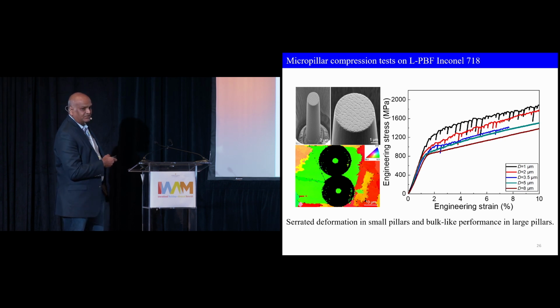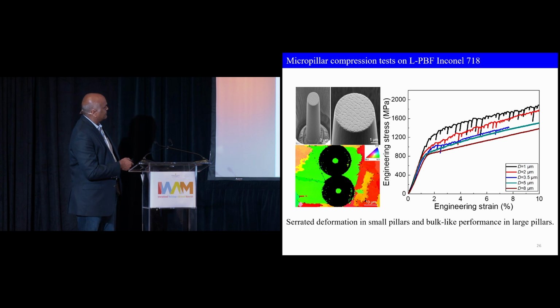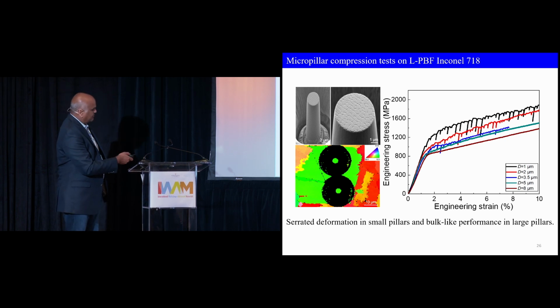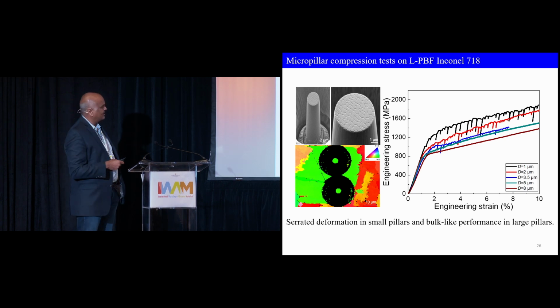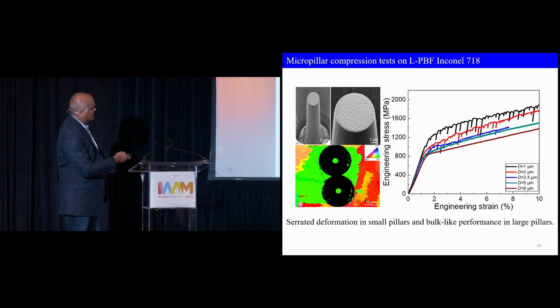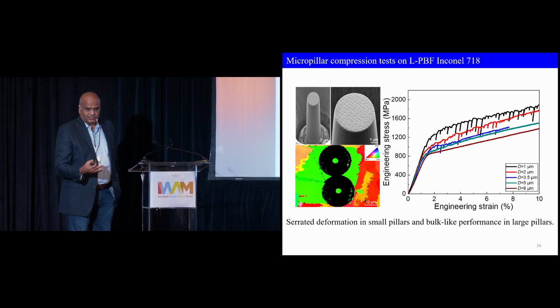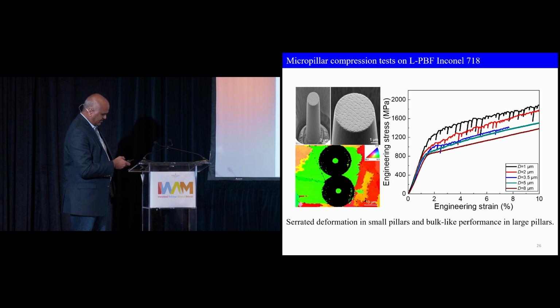So these are engineering stress-strain curves, but these pillars are now 2 microns or 1 micron diameter, so very, very fine structures. So obviously you can see as the pillars get smaller, the black one is 1 micron, you see large serrated flow because of the size itself. More importantly, as the size gets smaller, it gets stronger. Smaller is stronger in this case.